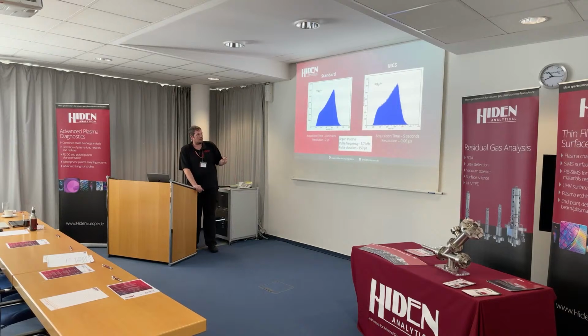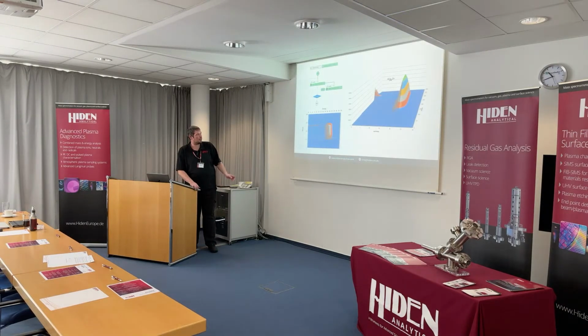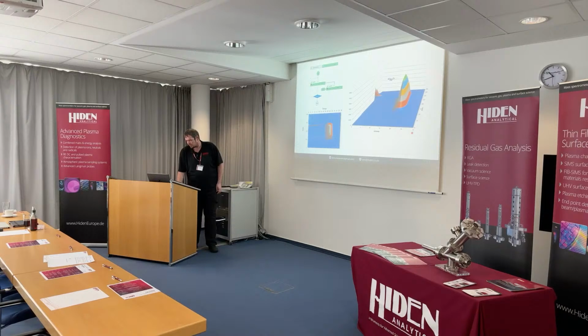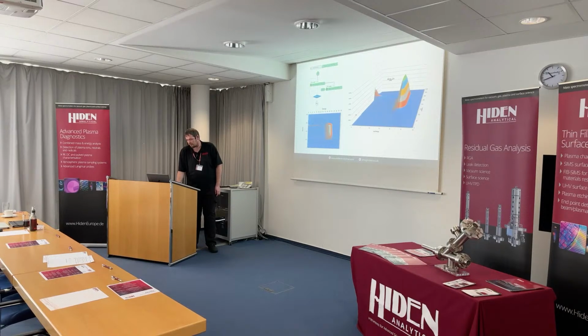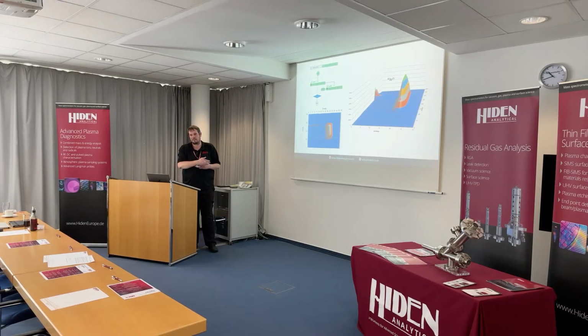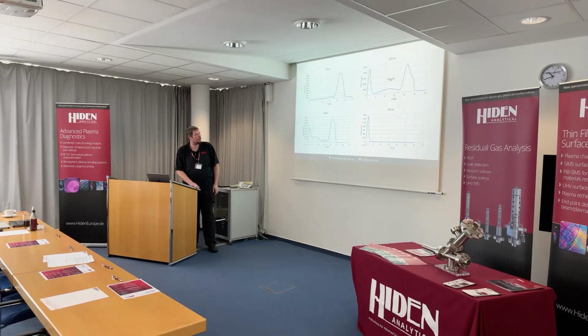So this is looking at a single energy, but it's also possible to do the same scan for multiple energies, and then plot them in 3 dimensions. If we do that, that's what we get here. So we've got ion energy down here and time going up there. If we take slices in this direction, because it acquires the data this way, if we take the slices horizontally through here, we've acquired all of the ion energy distributions at the different points in time. I think this one was a 1 microsecond resolution, and after you've acquired the data, you can then extract the ion energies after the fact. So I just chose some where they look a little bit different.